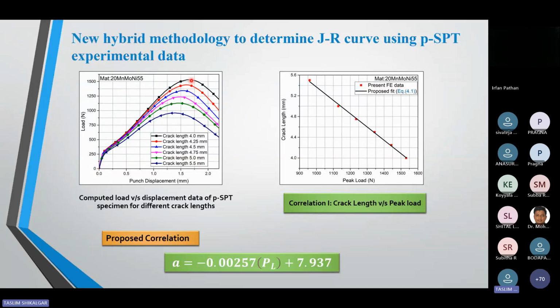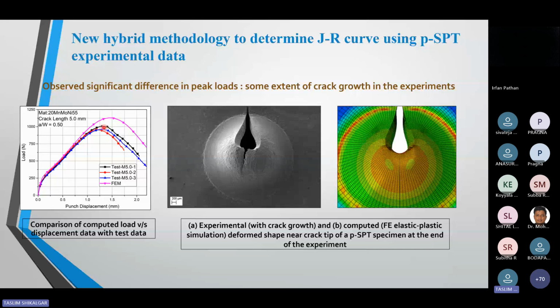You can see this. If my crack length is increasing, my peak load is decreasing. So from this load displacement data, I calculated the peak load for each crack length and plotted it as crack length versus peak load data. Here I observed the first correlation, which is linear, and I generated this correlation: a is a function of the peak load. And this correlation is very important. If I put in the experimental peak load here, you see the experimental peak load is always less than the numerical peak load.